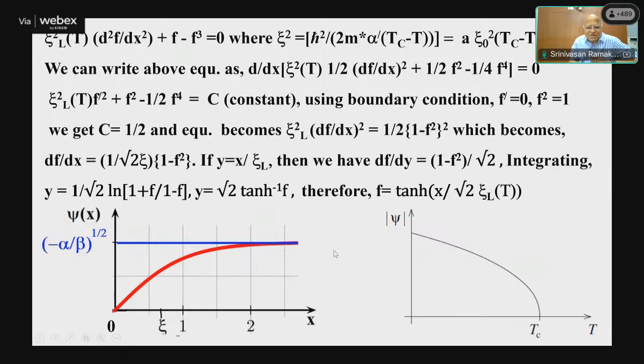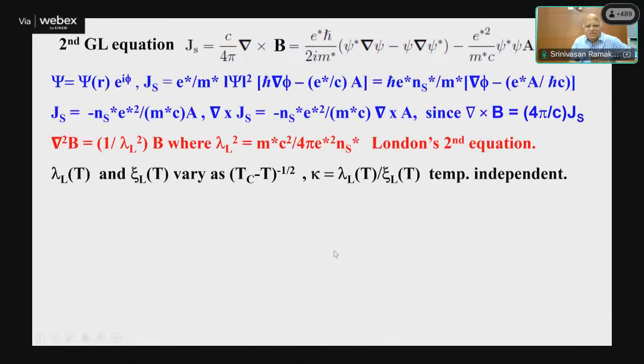And similarly, when you look at the second GL equation, where we got this by varying the vector potential, here you get this London's equation, del squared B equals 1 by lambda squared B. So lambda GL and xi GL, the Ginzburg-Landau penetration depth and Ginzburg-Landau coherence length, vary as (Tc minus T) to the power minus one half. Sorry.